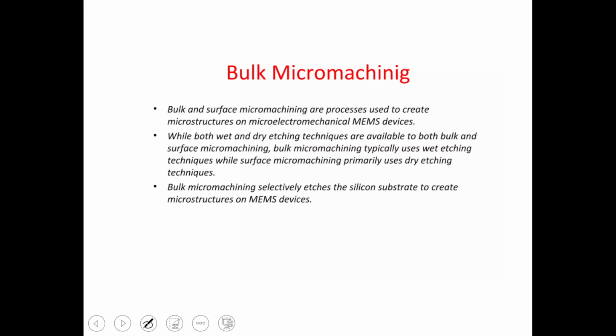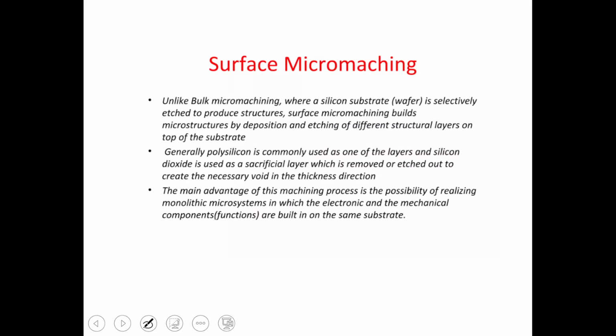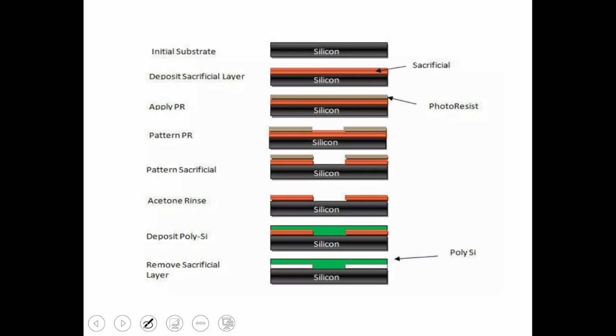Bulk micromachining selectively etches the silicon substrate, and we can transfer the microstructure to the MEMS devices. Another is surface micromachining. Unlike bulk micromachining, where the silicon wafer substrate is selectively etched to produce structure, surface micromachining builds on top of the substrate. Generally we use a polysilicon layer, and silicon dioxide as a sacrificial layer, which is removed or etched out to create the necessary void in the thickness direction. So this is the fabrication step.